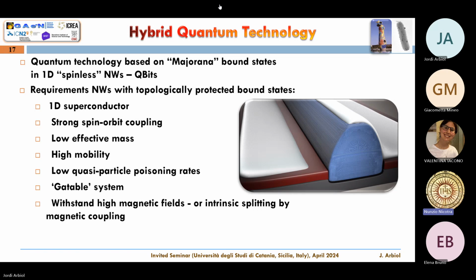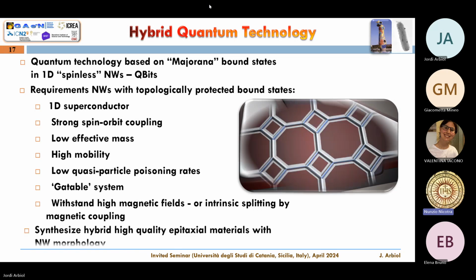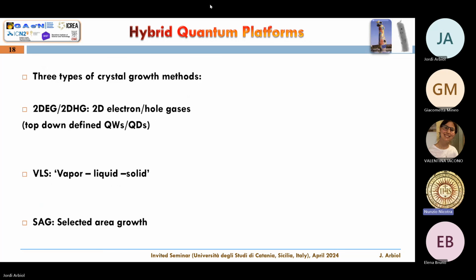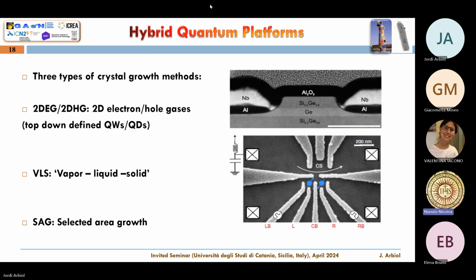But the idea is that you should grow a nanowire. This is a nanowire with a semiconductor, a high mobility semiconductor. And then on top, you try to grow a superconductor. Okay? And this is the 1D superconductor because you will grow it on top of a nanowire. That's the main idea. Let's see. And then what you will try to create is this type of networks in which, okay, we should have here these Majorana fermions. So let's see the different technologies or different approaches that you can get in order to get the type of morphology I was showing you before.